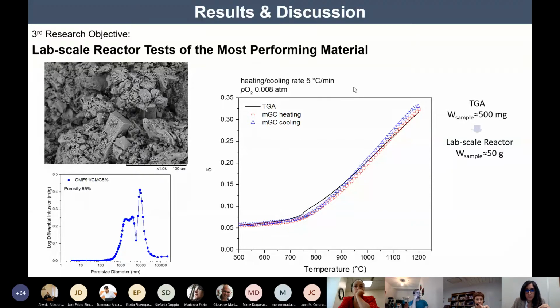Just for the sake of briefness, I'm going to show you just a few results. These are the profiles that we obtained from the reactors, and the black line is the TGA analysis. We can see the profiles are almost overlapped, and this is quite an exciting result, considering that we moved from a sample mass of 500 milligrams to a sample mass of 50 grams in the laboratory scale reactor test.